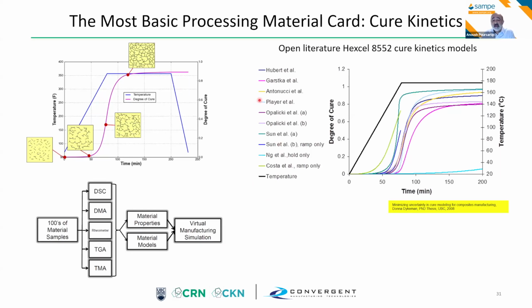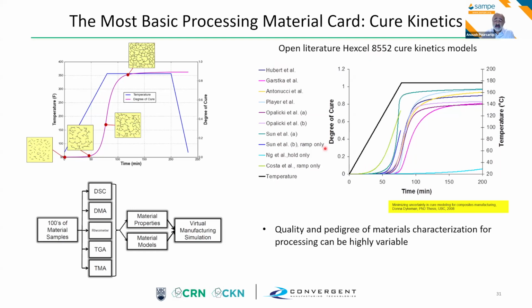Key point to make, and this is old, this goes back to 2008. Corina Cukelman did a nice job going through the literature, finding every 8552 Cure Kinetics model that existed at the time and just comparing them. And what you see is that sure enough, they all predict that the material cures, but you can see a wide range of predictions, including one which is way off. So pedigree, quality really is important.